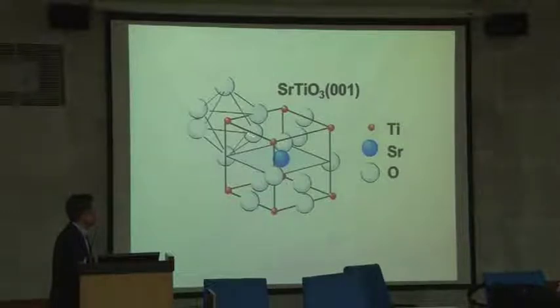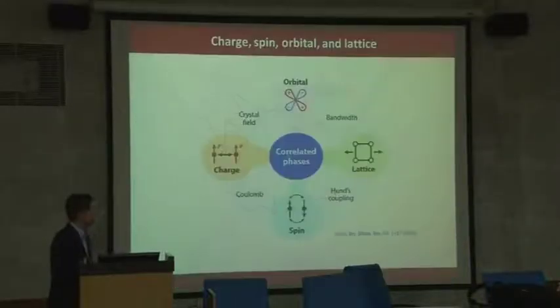And then when you have this crystal structure, and you look at these two dimensional planes, either you have TiO2 at the surface, or strontium oxide at the surface. You have two different types of surface that can be created. So this is another thing I'm going to talk about later, and this forms termination of this material system, and then you make a two-dimensional electron gas or two-dimensional hole gas, and that's one of the topics I'm going to cover at a later stage of this.